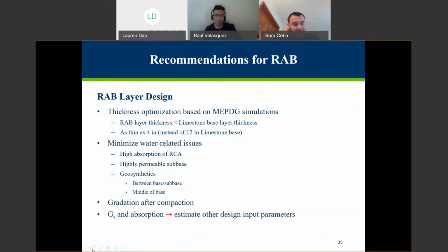And one thing that our study found, you need, for instance, resilient modulus input or permeability input that you need to put in your pavement ME design. But we developed some equations and correlations so that a majority of these input parameters can be estimated by just measuring the specific gravity and absorption values of these materials. Next slide, please, Ron.